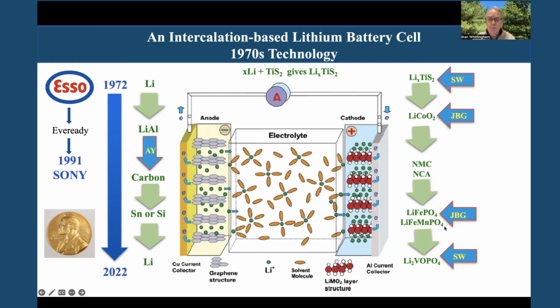John Goodenough also came up with these lithium iron phosphates. These are more stable materials, which I'll get into in a moment, but they store much less energy. But they contain no expensive cobalt, no expensive nickel, so there's a big push there to make them work for grid storage. We in my lab were looking at solving this energy storage drop by inserting 2 lithiums into these phosphates. And to do that, we need a transition metal that can go from, say, 5+ to 3+, just as vanadium does.